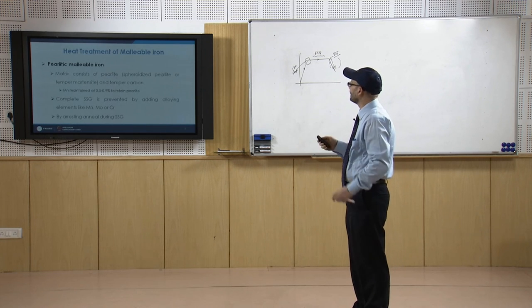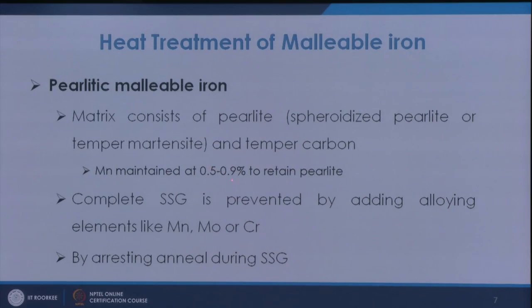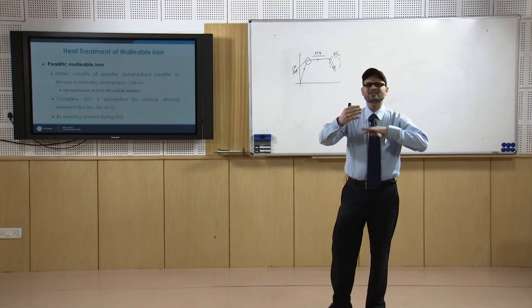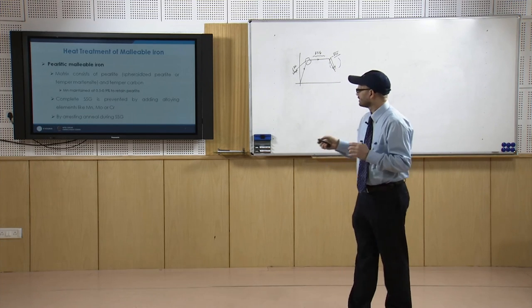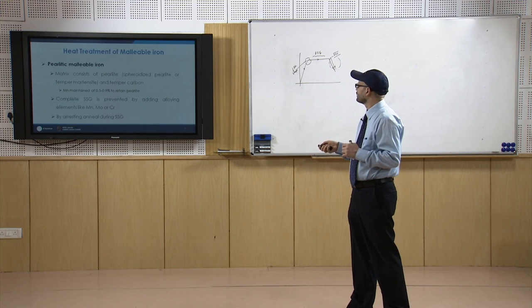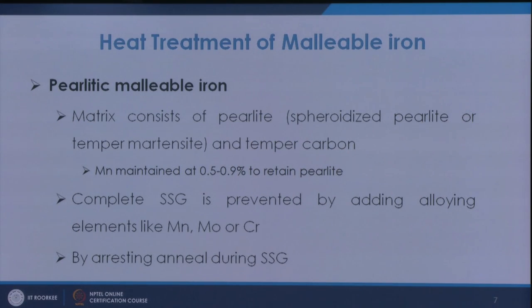Also you are adding manganese. If manganese is maintained at 0.5 to 0.9%, in that case it retains the pearlite. So complete SSG is prevented also by adding alloying elements like manganese, molybdenum or chromium. If these alloying elements are there, they try to give you the pearlitic matrix. So one way is that you arrest the anneal during the second stage graphitization. Another is that you are preventing this second stage graphitization, where otherwise you could have got the ferritic matrix. You are getting the pearlitic matrix because of the composition having manganese, molybdenum or chromium.